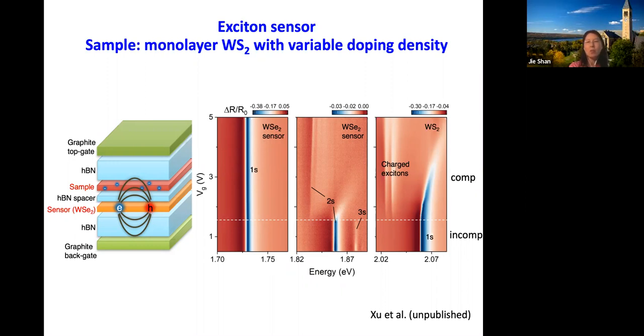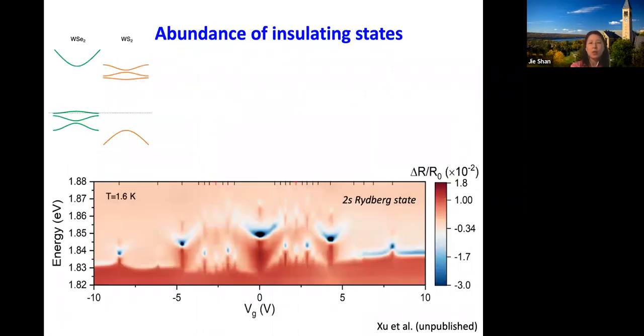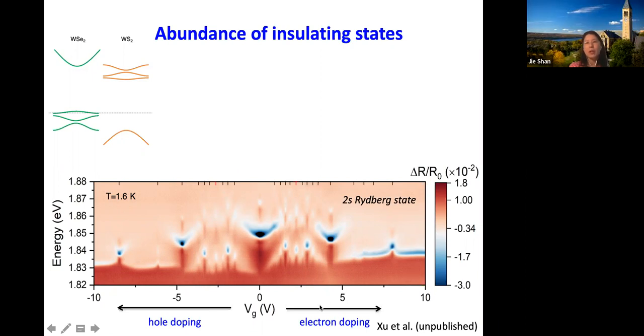Okay, so now let's apply this technique to our moiré system. And this is what we saw. What I'm showing here is the 2s state from the sensor layer as a function of gate. What the gate does is only change the doping in the moiré system, okay? The positive gate voltage dopes electrons into WS2, and the negative voltage dopes holes into WSe2, okay?